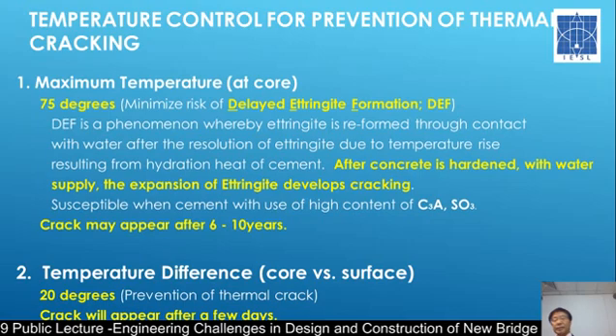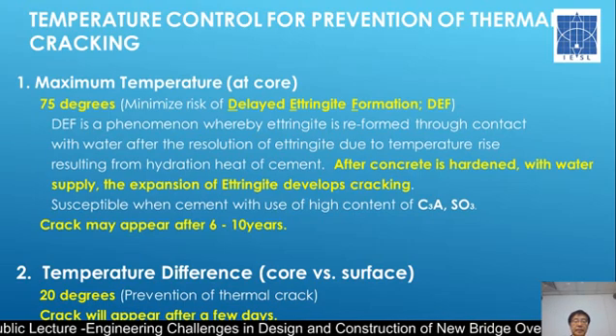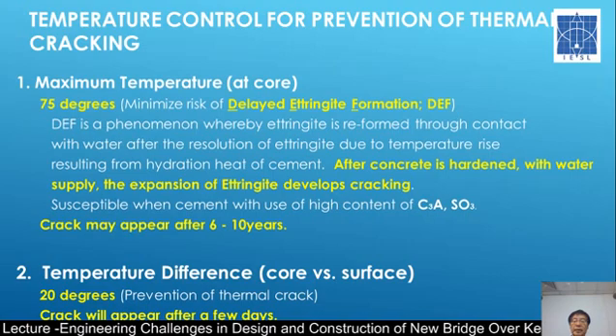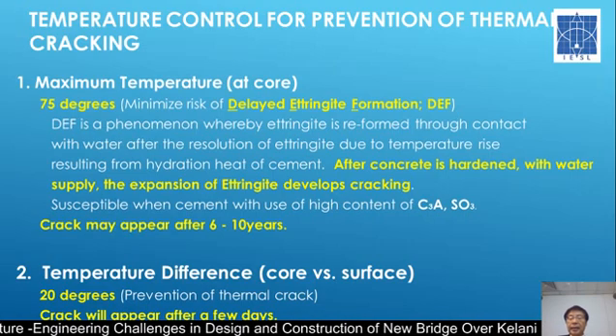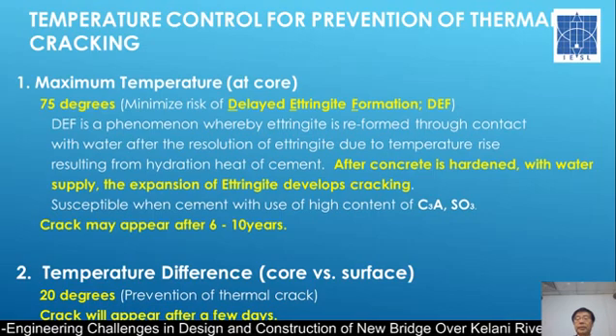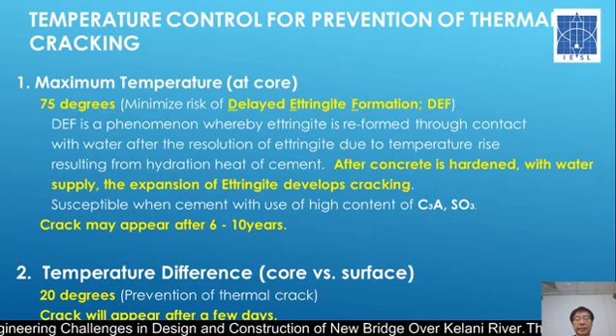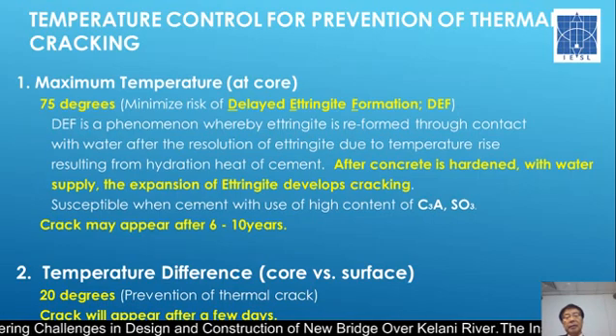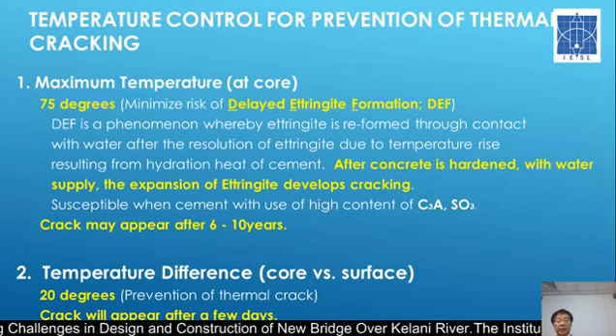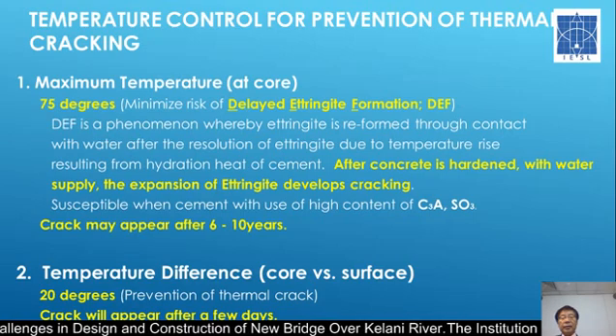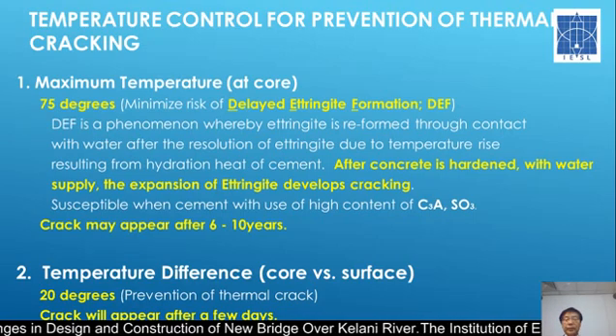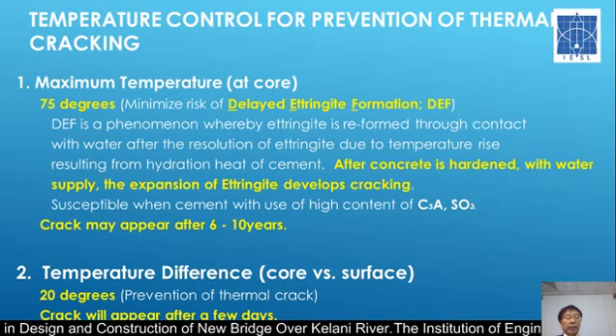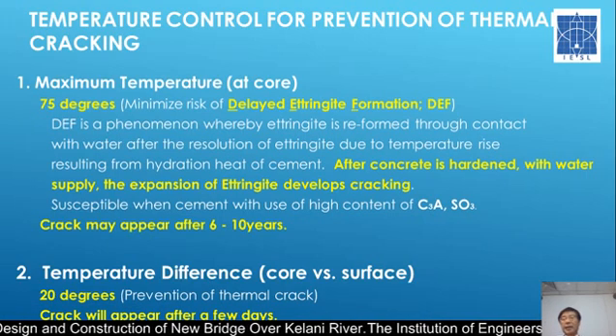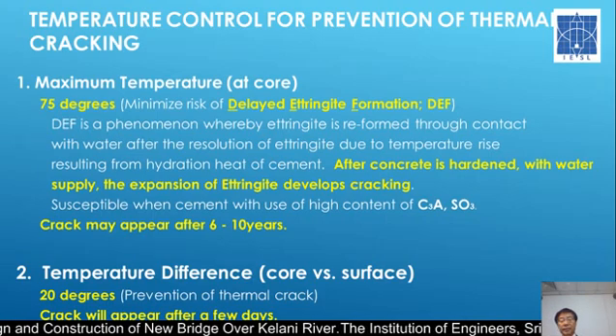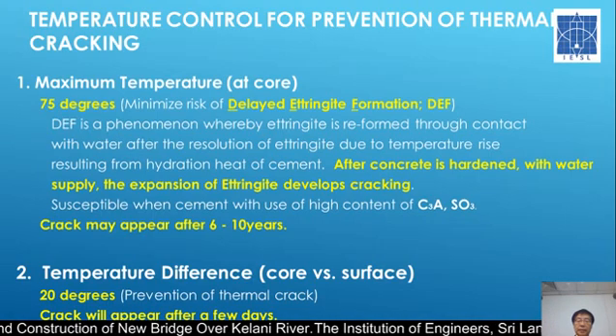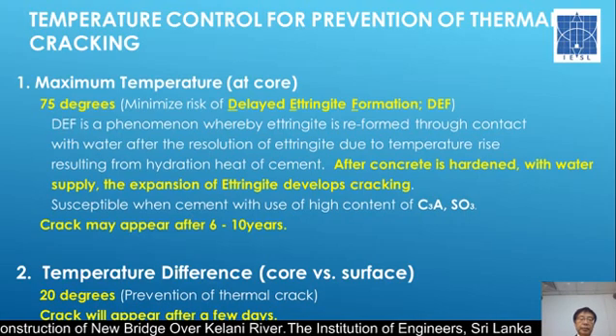I'm not sure whether you know this cracking, but it is a chemical action that occurs when cement containing alkali or C3A or SO3 is used, and the temperature is high when they are casting, and when water is added after the concrete is hardened, the ettringite expands and cracks. This cracking is very dangerous because the crack may appear not immediately after the casting, but after a few years, sometimes 10 years. So this is a very important criterion that we need to strictly follow.